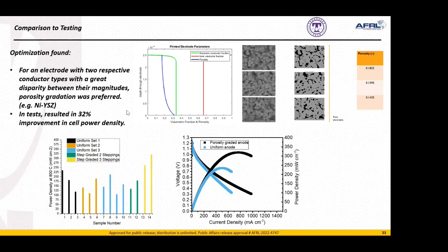Now, we also found through our optimization a preference of porosity gradation versus compositional gradation in a conductor that has two phases with fairly disparate conductivity. So in a nickel YSZ anode, the nickel electronic conductivity is about 6 orders of magnitude higher than the ionic conductivity of the YSZ. In these type of scenarios, porosity gradation was actually preferred.